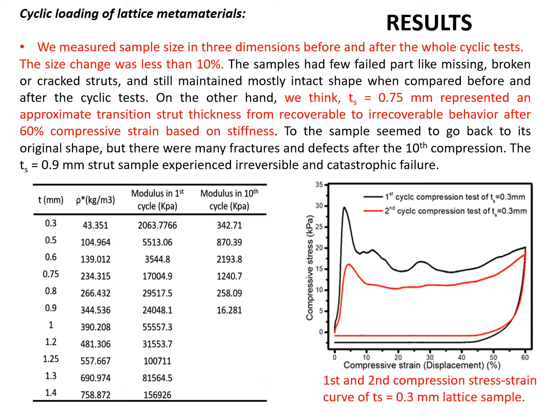We measured the sample size in 3 dimensions before and after the cyclic tests. The size change was found to be less than 10%. As a result of our cyclic tests, we think that the 0.75 millimeter strut thickness represents an approximate transition value from recoverable to irrecoverable behavior after 60% compressive strain based on stiffness. This behavior is shown on the table on the left.